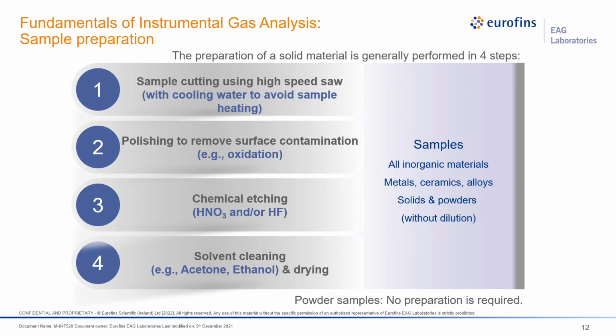A solvent cleaning is performed to remove any contamination that might have occurred during sample preparation, followed by drying. The most common example could be a copper matrix, where we need to remove the oxidation layer, followed by etching in an acid, and then keep the sample stored in acetone until we are ready to do analysis. Powder samples do not require any preparation as such and are normally packed in capsules for analysis. Relatively less complex sample preparation is one of the strengths of the IGA technique.